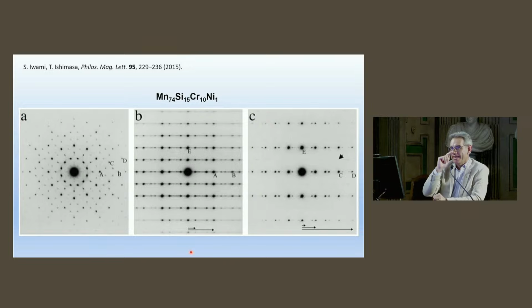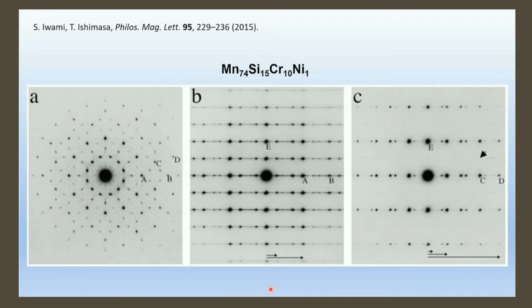So the idea is to try to synthesize a diamond starting from a metallic seed with a composition able to produce a quasicrystal, and see if the conditions used to form diamonds are able to preserve and form a quasicrystal. So it seems another impossible idea. So I decided to contact the guys who are able to synthesize diamonds in Russia, and one of them accepted and produced this kind of diamonds.